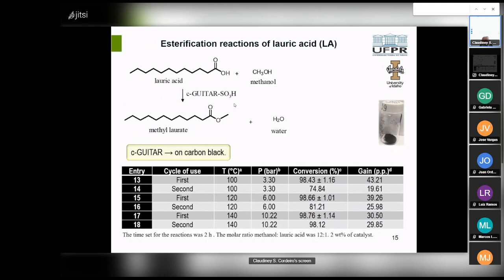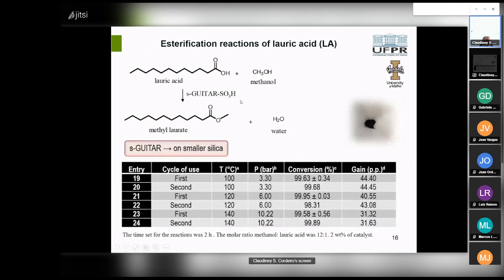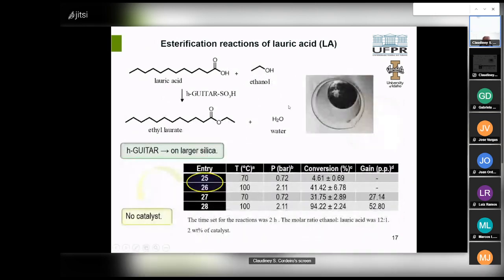The reasons for this loss of activity still need to be studied, but it may be related to leaching from guitar. The results of the first and second uses are similar, as with the use of larger silica. These preliminary results indicate that silica may be a better choice of support than carbon black.